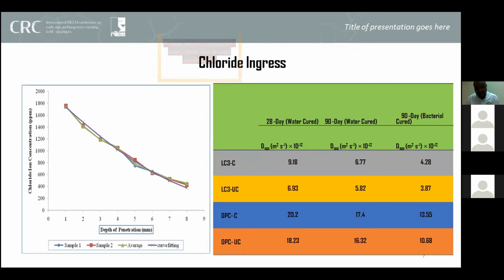The chloride ingress test was conducted on mortar prisms cast and subjected to accelerated chloride ingress. After exposure to the chloride media, the mortar prisms were sliced into portions of 1 millimeter each, and the amount of chloride in each piece was analyzed, with the chloride profile made using Fick's second law.